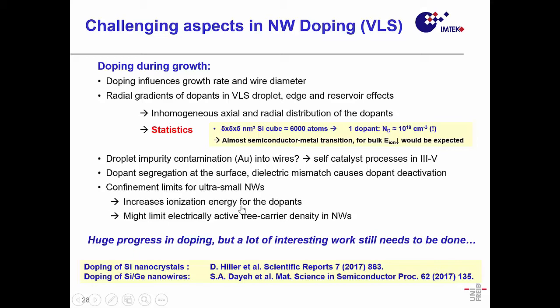So the challenging aspects in nanowire doping based on this VLS process is the influence of the doping materials on your growth rate. It's also affecting the wire dimension, the radial gradient of the dopant in the droplet, but also then how it's pushed out. You have an inhomogeneous radial and axial distribution of the dopants.